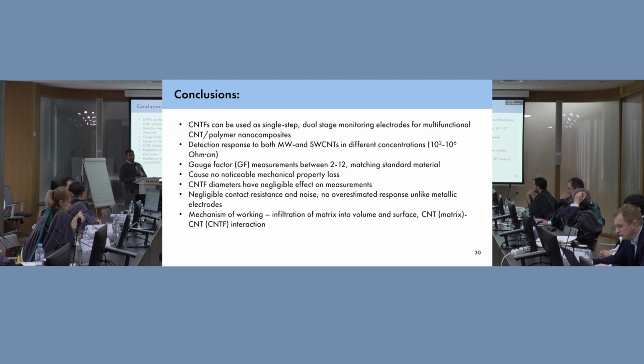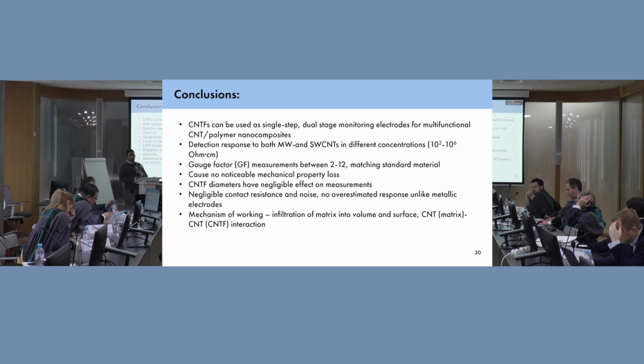Overall, we see that CNTFs can be used as a single-step dual-stage monitoring electrode system for multifunctional property measurement of CNT nanocomposites. Our detection was similar for both multi-wall and single-wall carbon nanotube composites at different concentrations. So we see that we get a response from quite a wide range of electrical properties. Our gauge factors were between 2 to 12, which are quite good, relating to literature very cleanly.